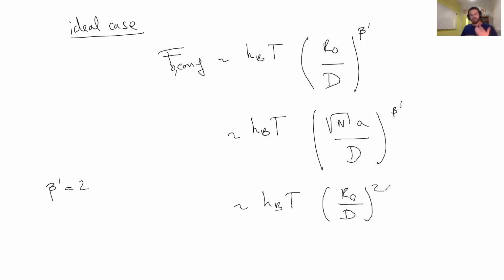And in fact, you knew that this is true because we did the Schrödinger tutorial. I think it was number 5. We found in the ground state dominated situation where you have a chain that is ideal and that is very confined in a narrow slit, we found that the probability was something like exponential minus the number of objects, a squared. In the ground state dominated, you were taking the first, okay.